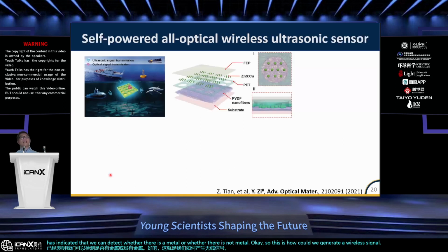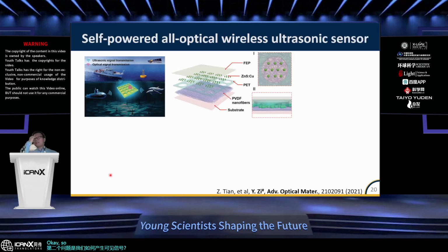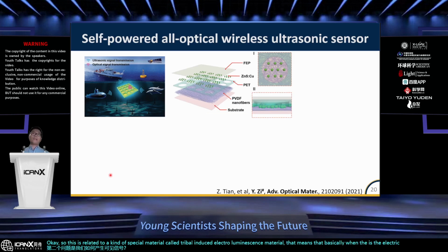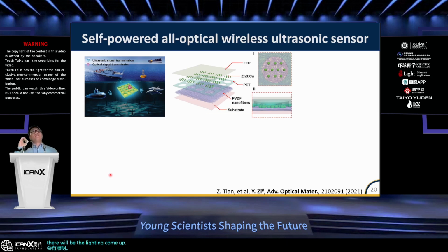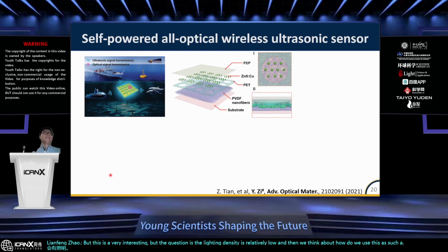And second question is, how could we generate the visible signal? This is related to a kind of special material called the tribo-induced electroluminescence material. That means basically when there is the electrical field generated by the triboelectric charge, there will be the light coming up. But this is very interesting, but the question is, the light intensity is relatively low. And then we think about how could we use such a low intensity light generated from the triboelectric charge.